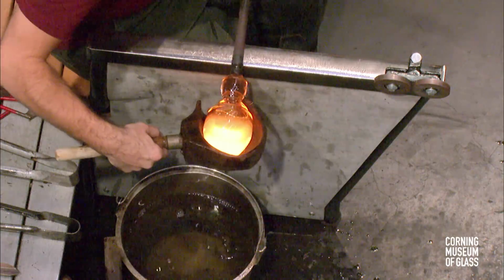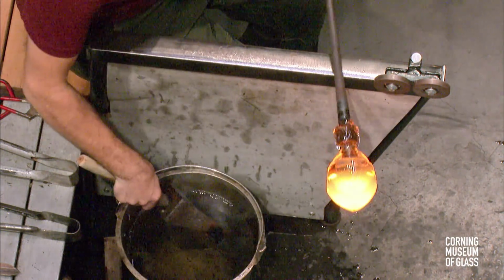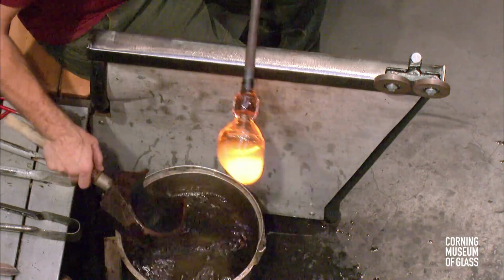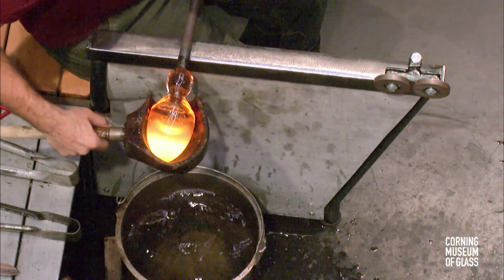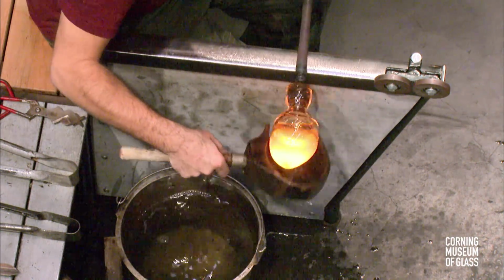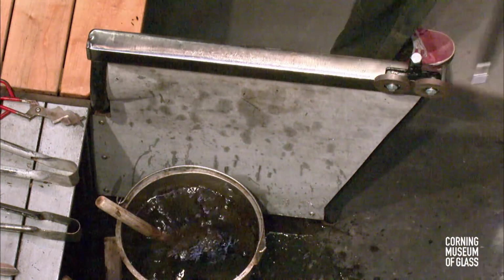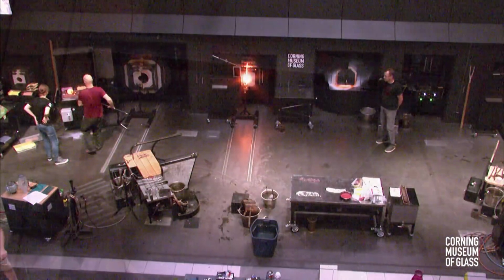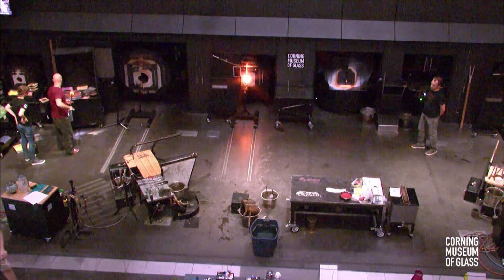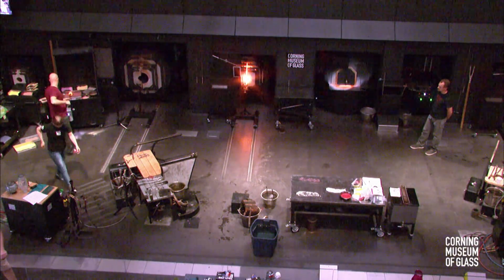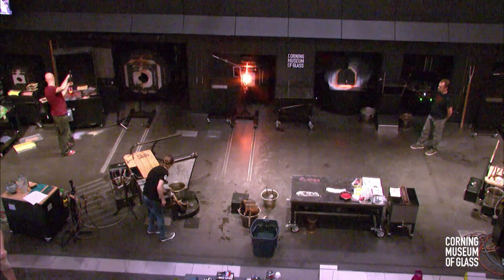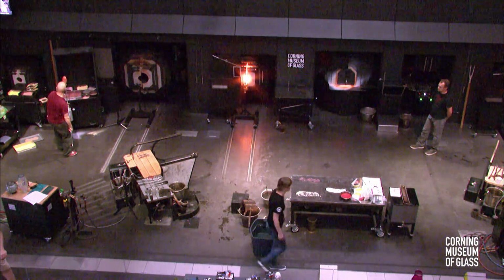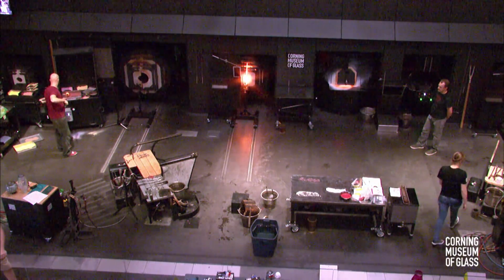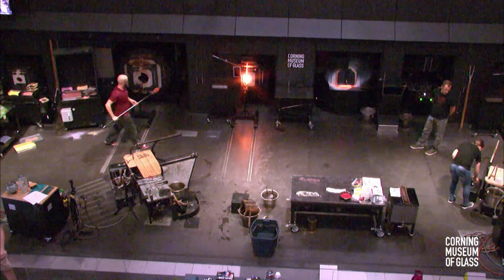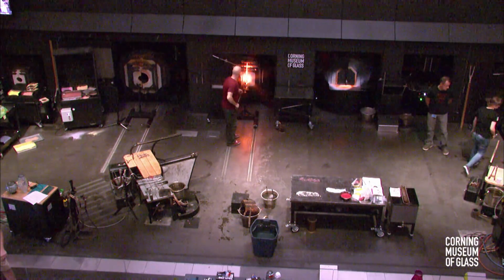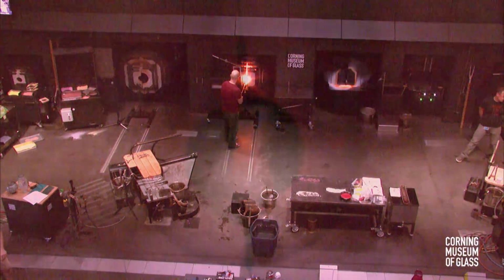Quickly, he sits down at the bench. He uses a tool called a block just to get the glass under control. This tool is made out of wood. It might sound like a bad idea to shape glass that's 2,000 degrees with a piece of wood. It works very well though, mainly because we keep these tools soaked in water all the time. When the heat of the glass comes in contact with that water, it creates a thin little pocket of steam that the glass is riding on top of. And as long as we continue to re-wet those tools, those wooden tools will last us for quite some time.